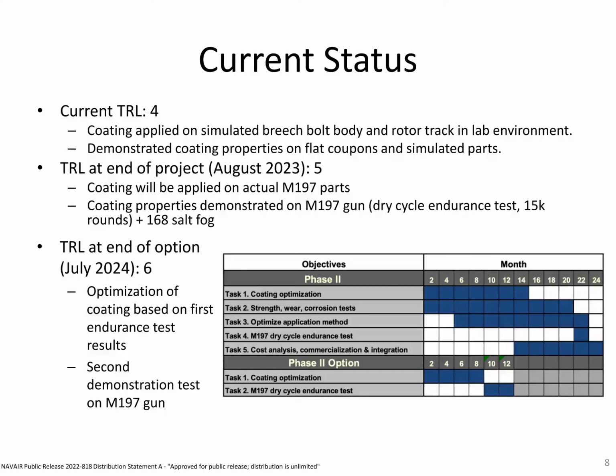At the end of phase 2, we will be coating an actual gun with our prototype coating, and we will be doing a dry cycle endurance test of 15,000 rounds plus a salt fog post-fire test. After our phase 2 option, we expect to be at TRL 6. During the phase 2 option, we plan to further optimize the coating based on lessons learned during the dry cycle endurance test, and then coat another gun and do another endurance test with an optimized coating.